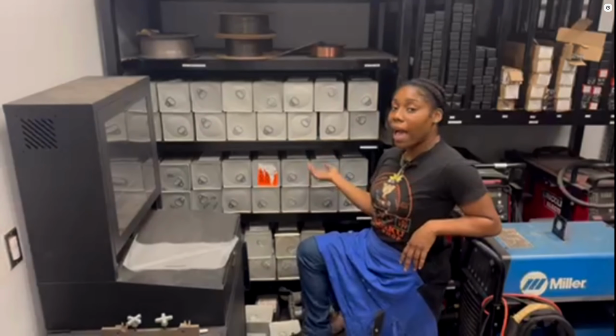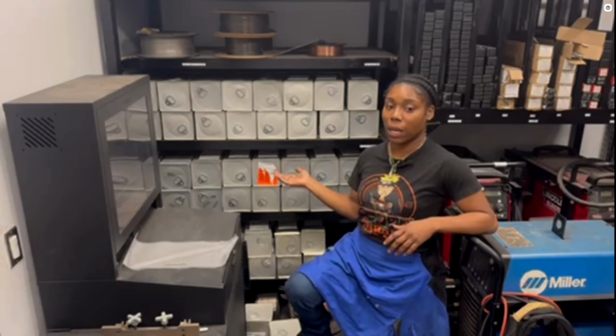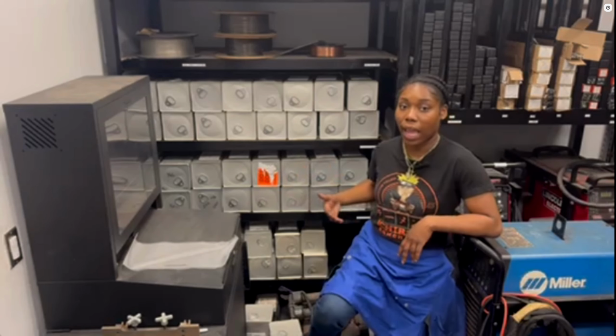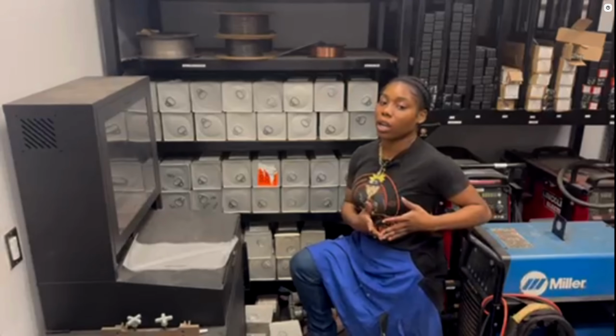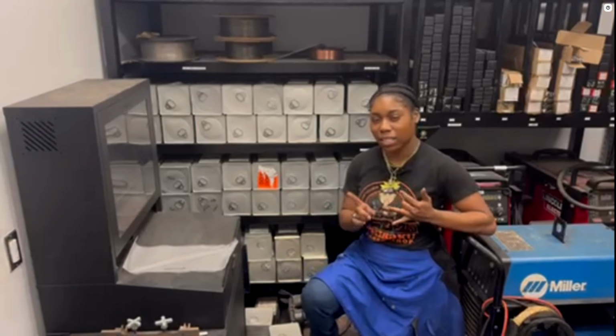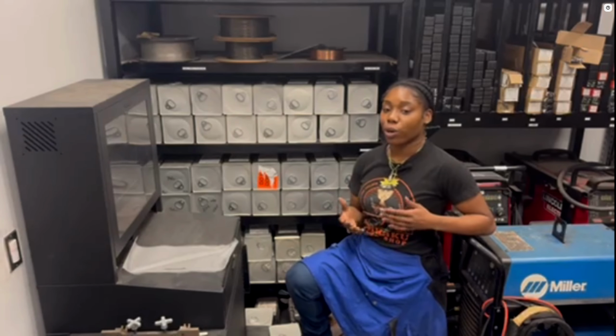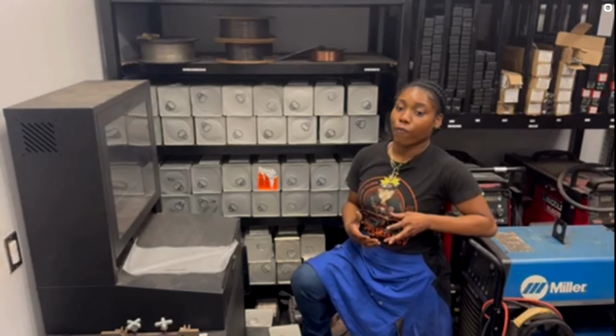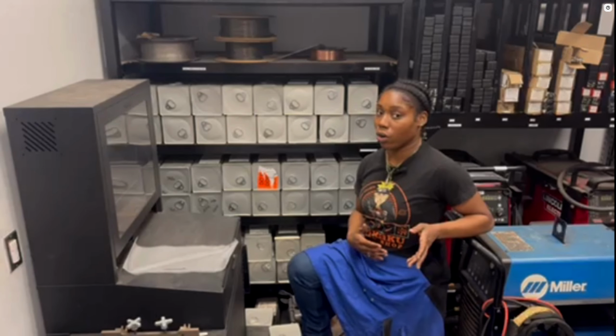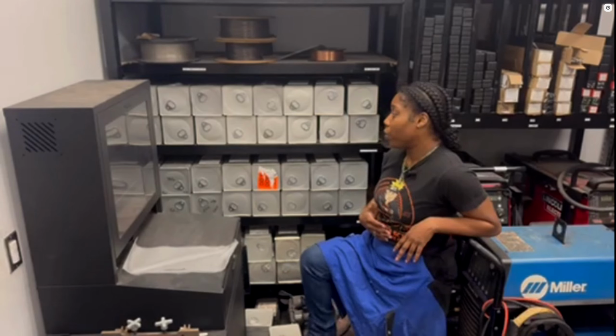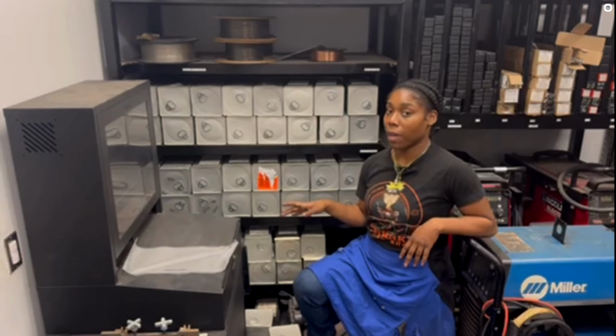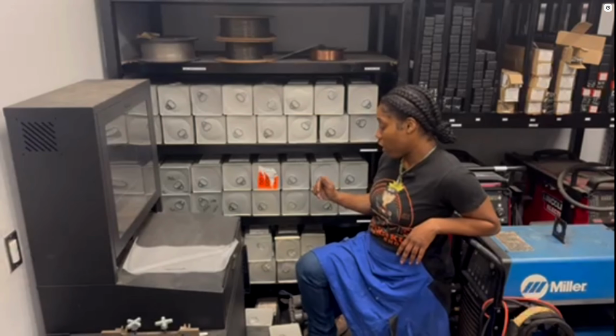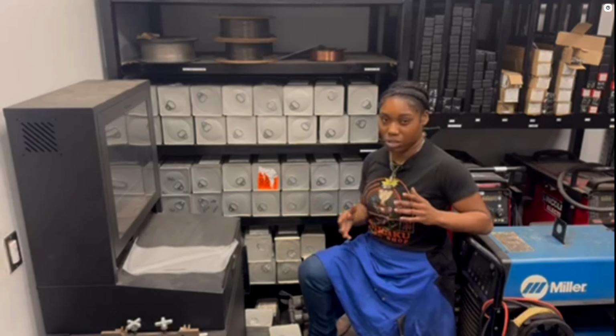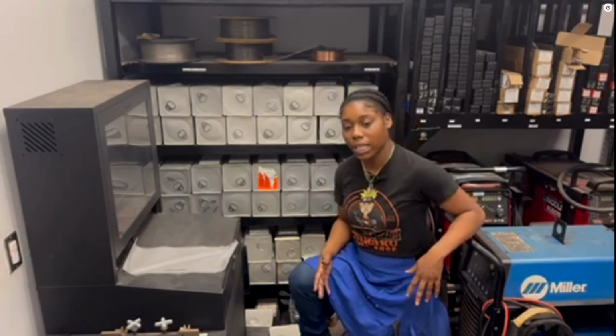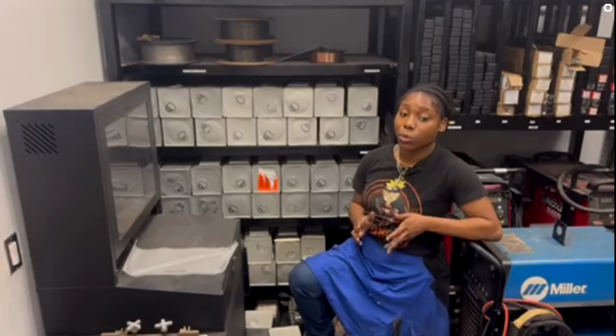So here we have some electrodes that we store at room temperature, mostly cellulosic and rutile. Some cellulosic electrodes are like the 6010, 6011s. They do require a little bit more moisture for arc characteristics compared to low hydrogen electrodes. So they don't necessarily need to be baked or rebaked. As far as the rutile electrodes go, those are like the 6013, 7014s. Those are moderately sensitive to moisture.